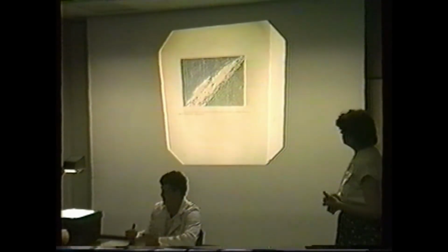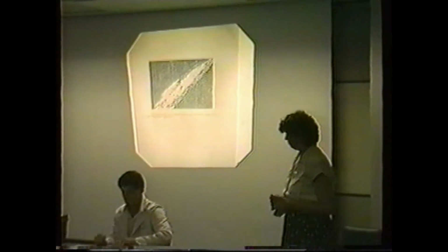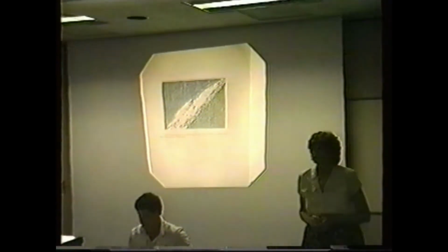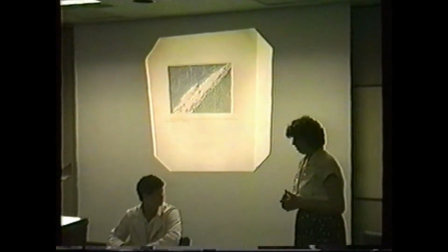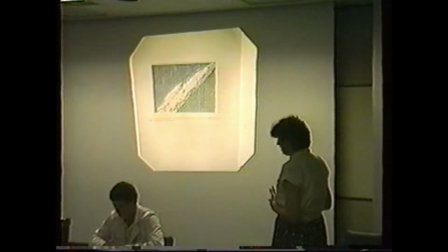So, how can you tell that this was applied in the 1500s and say not the 1800s? Basically, what we had to do is then look at some of the suspended particles in the matrix. And most of these particles were irregular shaped. And this is in contrast to later centuries, when they would have been manufactured to spherical dimensions. So, you're basing your opinion on only one pigment analysis? I think that's rather weak, okay? Do you have any other evidence for this work?